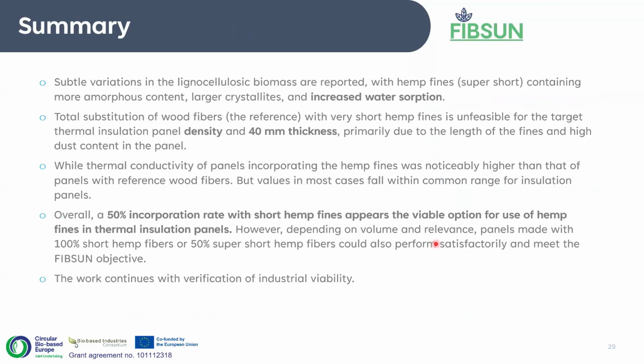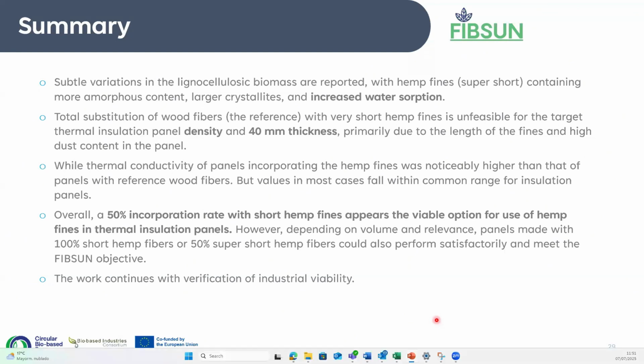So to summarize in general for this particular section, we did find variations across fractions of hemp stock, from fibers to fines and whatnot. Of course, shives also, which I know have been studied, also have some differences in properties. So we cannot totally substitute wood fibers with very short hemp fibers, especially when we look at all the results put together, primarily because the fiber lengths are too short and the dust content is higher in this regard.